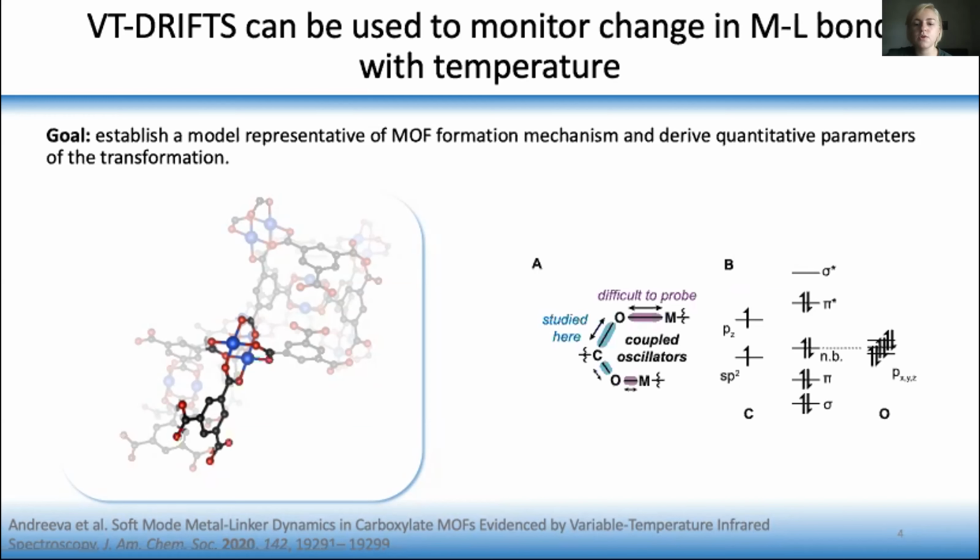And accordingly, stronger metal-oxygen bond interactions would also enhance the CO bonding by distributing the antibonding density away from the CO bond and cause a blue shift, whereas weak metal-oxygen interactions should cause red shifts.